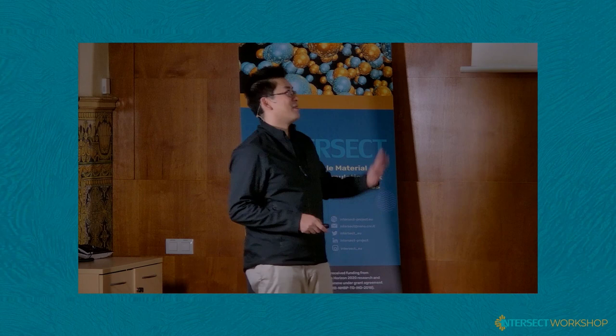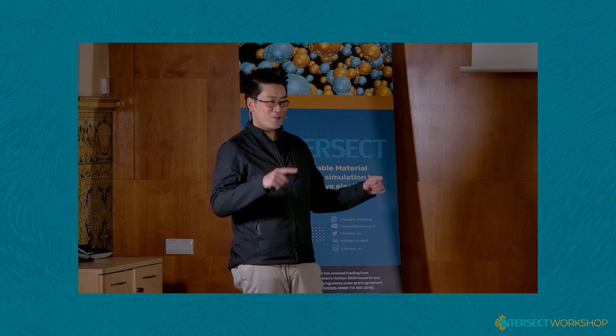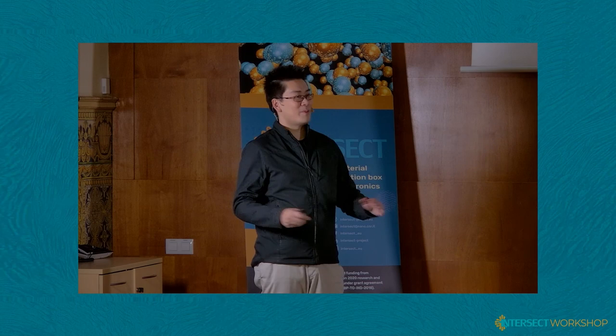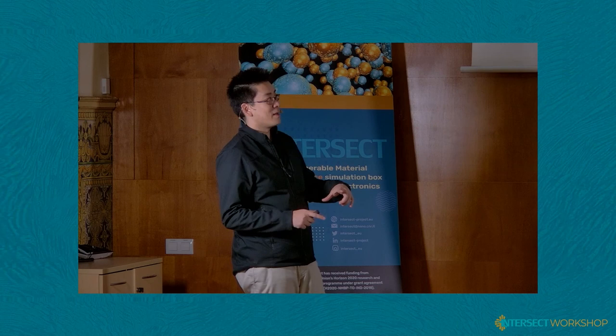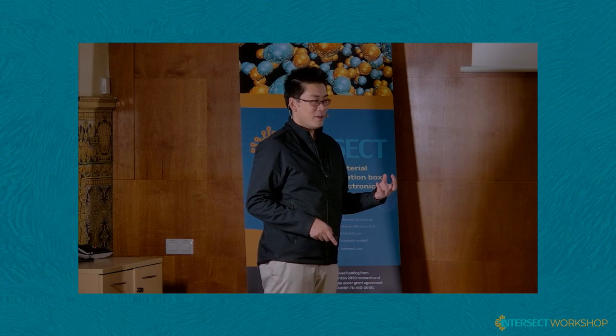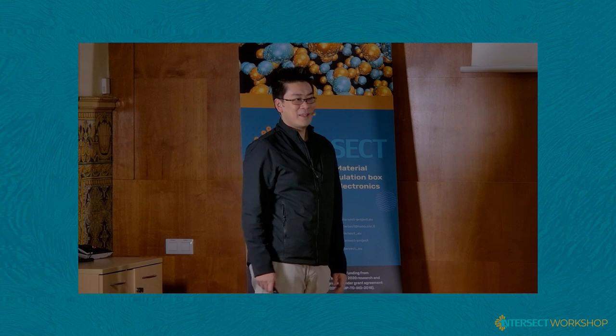I think a big reason why those images I showed look like that is because they are using uniform nanotube distributions, which they cannot have experimentally. I didn't put the images up because the structures that have nanotube distributions for the length are much newer. But the moment you have shorter and longer nanotubes, it changes wildly. You no longer have these rectangular effects. On top of that, there are a lot of techniques that they use to add disorder into the system. So you can put things in between the nanotubes and prevent them from being locally crystalline in that sense. Exactly.